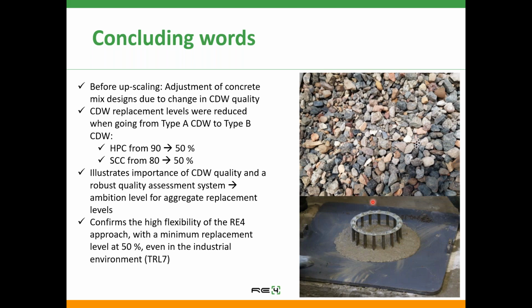The challenge with these aggregates is typically the water absorption, which is a bit higher than what at least we are used to in Sweden, where we often have very low water absorption values. But that can be handled, if assessed in the right way, for example by pre-saturation or by surveying how much water this contains, and then calculating with it when you proportion your concrete and count how much water you need. It doesn't need to be such a big issue. We also noticed that when using a CDW of a little bit lower quality, we had to reduce our ambitions on replacement. That is also interesting, because it is a confirmation of this quality assessment system.